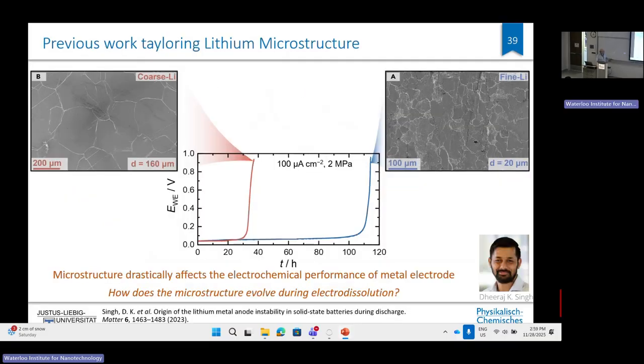We looked into that, and Dheeraj made some coarse-grained lithium and fine-grained lithium, where still the fine-grained lithium, you see, has quite big grains with 20 micron diameter. He was never able to make smaller-grained lithium because lithium is really growing fast. Its grain growth is extremely fast.